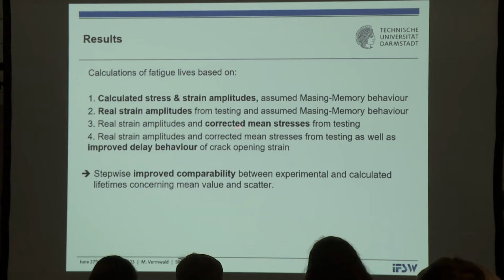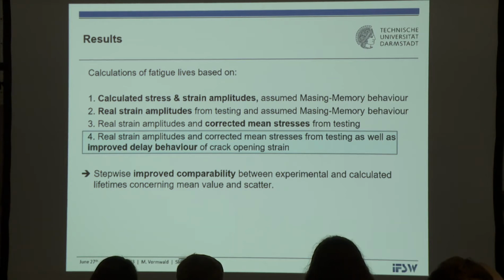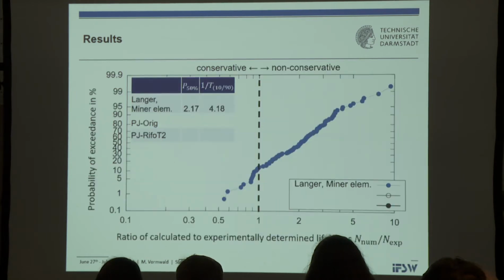If we take the mean stresses from the experiments, things are becoming better, and the only report here will be on the real strain amplitudes. No machine uncertainties in the control circuits and other things are then incorporated in our comparisons, and corrected mean stresses are taken into account, and this improved delay behavior of crack opening strains. And this is what I'm going to show now.